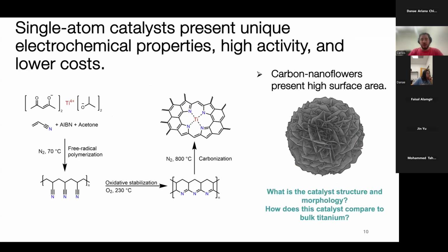The way that we're creating these catalysts is, we're mixing Ti4+ reagents with acetone and other reagents for this reaction. Initially, we do free radical polymerization, then we stabilize the polymer, and then we carbonize the polymer. And what we hypothesize is that what we end up with is a titanium that is ligated to 4 nitrogens in a carbon matrix. And we spend a lot of time trying to prove that this is the structure that we have. And I'll talk more about that later.